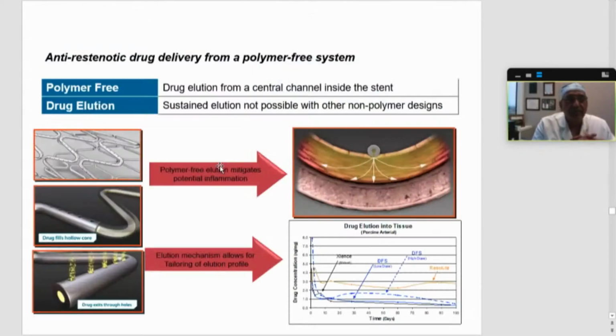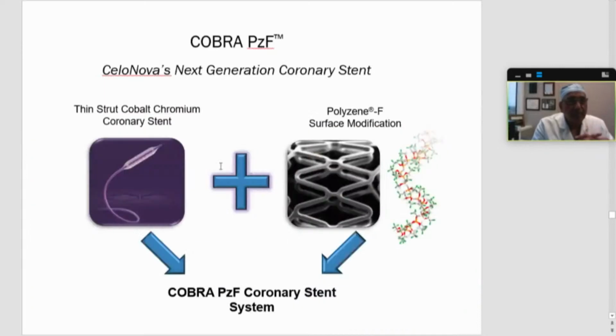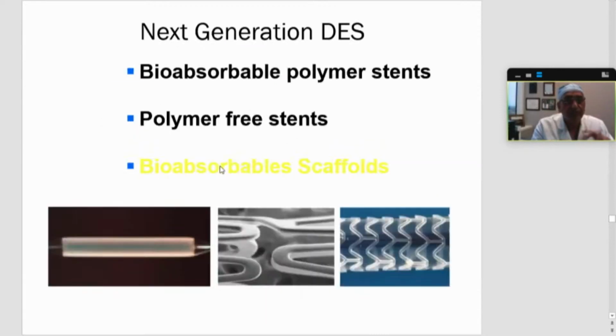and that leads to vessel transfer of the drug and possibly also can shorten that. There's this novel idea where there are holes made into the stent strut, and the drug elutes from those holes on the abluminal side over time, what we call a drug-filled stent. Cobra PZF is a very interesting novel technology. It uses a thin strut cobalt chromium coronary stent, but then it is coated with a Teflon-like material called polyzene F, and that potentially, without any drug elution, leads to improved rates of restenosis down the road.